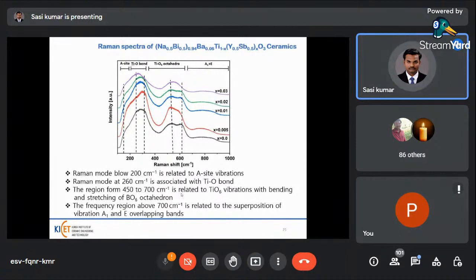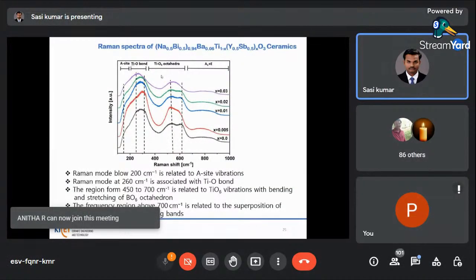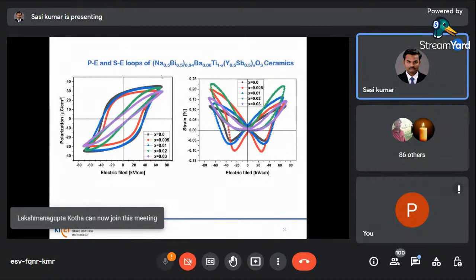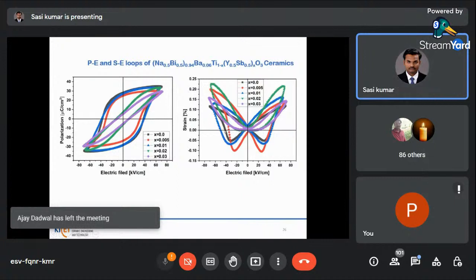So these materials show Raman shifts around the A site and TiO6 site, and different Raman modes are compared to the previous report, which is well established with these compositions. And then this is the PE loop and SE loop of NBBT doped with yttrium and Sb doped materials.